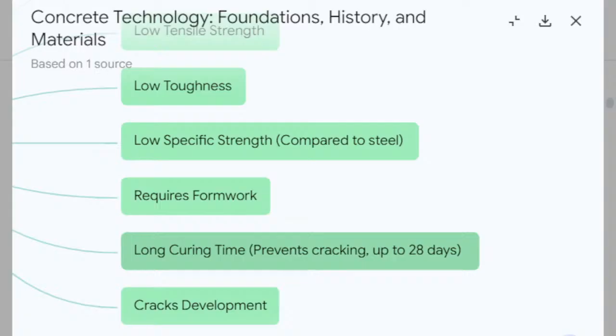Now, while some cracks are minor and just superficial, we often call them hairline cracks, and they might not be structurally significant. Others can be wider or deeper and potentially compromise the structural integrity or the long-term durability of the element. How do they compromise durability? Well, critically, cracks act like tiny highways, allowing harmful substances to get inside the concrete. Things like moisture, chlorides from de-icing salts used on roads in winter or from seawater in coastal areas, or other aggressive chemicals. If these substances penetrate deep enough to reach the embedded steel reinforcement, they can cause the steel to corrode, to rust. And rusting steel expands, which puts internal pressure on the surrounding concrete, causing more cracking, spalling where chunks of concrete break off, and eventually, potentially leading to serious structural failure over time.